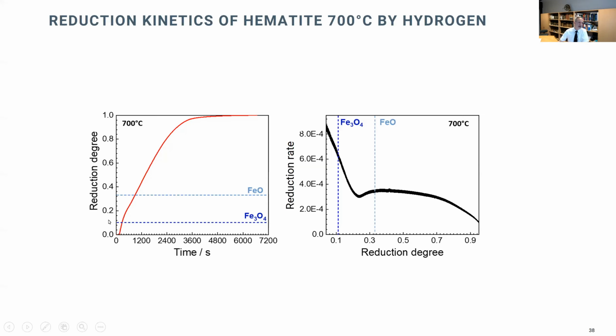And you see here the reduction degree plotted as a function of time, and here the derivative that shows you the reduction rate, so how quickly it goes against the reduction degree. And so when you arrive at 1, you would have pure iron. And you see that you go through different stages of the oxide. So you reduce it not directly, but go from hematite to magnetite, from magnetite to wüstite, which is FeO. And this stage, as you see here, is a very, very sluggish one, a very slow one. So there's something you want to understand better.